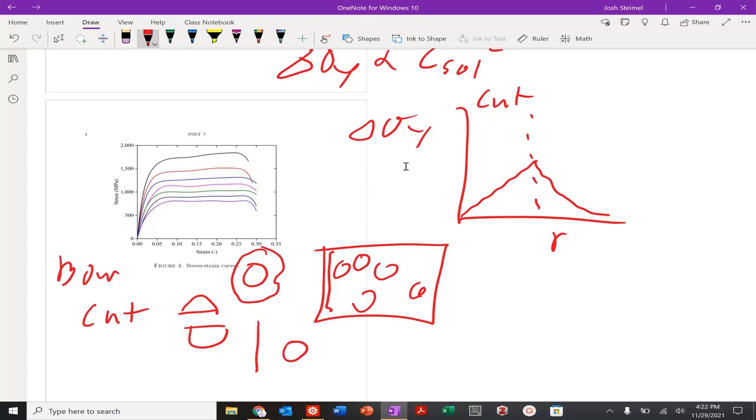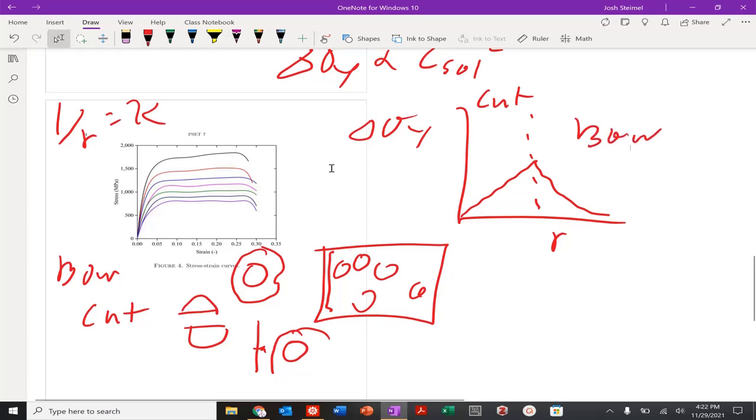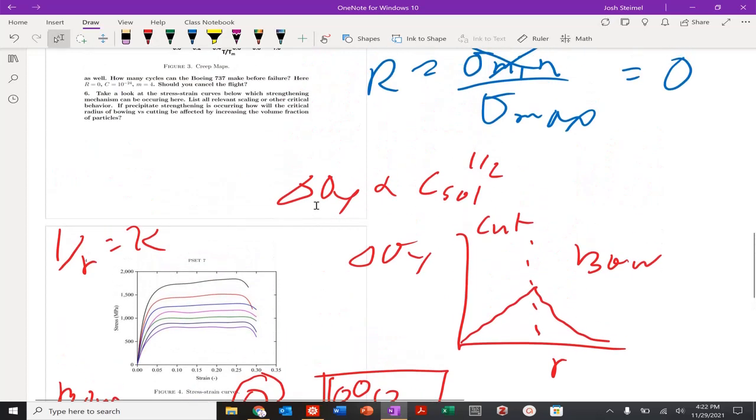Or my dislocation line can bow around the particle, so basically bowing around it and then creating that dislocation. So the dislocation line approaches the precipitate and it curves around. So bowing is curvature, so 1 over radius is my kappa. So I want to reduce that curvature energy penalty, so I want to bow around large particle sizes. Excellent.